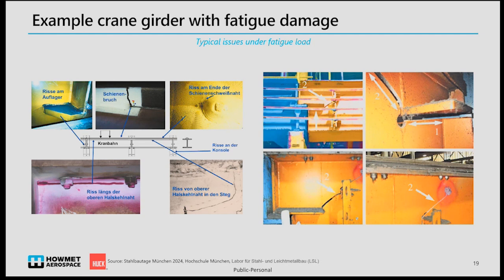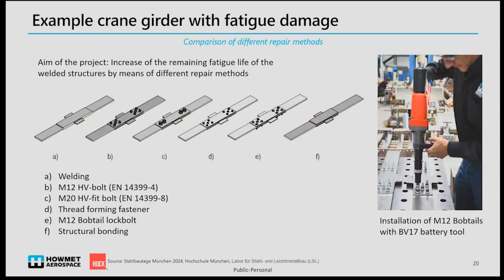In this research project, which was conducted by the University of Applied Sciences in Munich, there was the intention to investigate different repair methods for older welded structures to increase the remaining service life. In this project, 6 different joining methods were compared against each other. First was a conventional welding method, then a standard M12 HV bolt was used, also an M20 HV fit bolt, a thread forming fastener, and an M12 bobtail lock bolt, and as a last method, a structural bonded joint was tested. On the right-hand side, we see the installation of the M12 bobtail using a battery tool, and